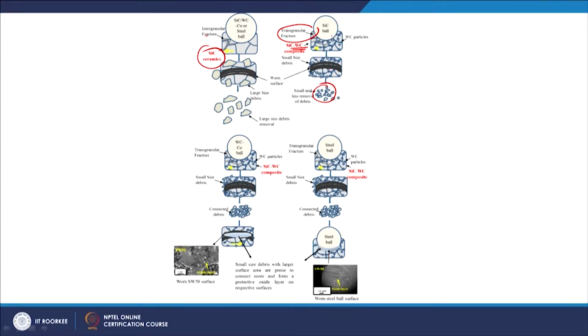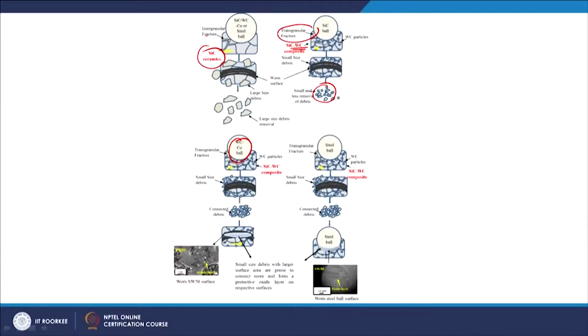Now, if you see the effect of the counter body against tungsten carbide cobalt ball, these composites again fractured by the transgranular mode, but the size of the debris is finer, and also with the increase in tungsten carbide content in the composite, particularly this SW50 or SW30, you can see these smaller debris with a larger surface area are more prone to connect and then form a protective oxide layer like this. So, you get a decrease in the wear. In case of the steel ball, these composites again fractured by the transgranular mode, and the smaller sized debris, they connect to each other and form a layer, and the layer is actually observed on the ball surface.